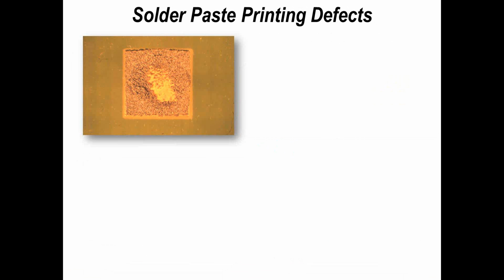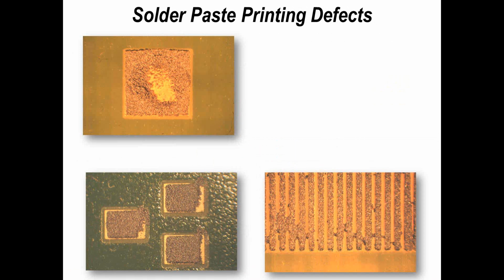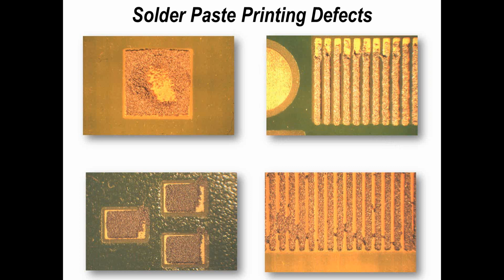Now, if we look at some simple process problems with solder paste and printing, I've given you some very simple ones here. First of all, we've got scooping on the top left. And this is literally where you've got either too big an aperture and too high a pressure, and you're literally drawing the solder paste out because the squeegee blade, even a metal blade, can scoop down into the aperture if you have too high a pressure. On the bottom left, this is to do with the stencil separating unevenly from the surface of the printed circuit board. And what it's doing is leaving some solder paste deformed and some solder paste still left in the aperture of the stencil. The same sort of fault is seen on the top right-hand image.